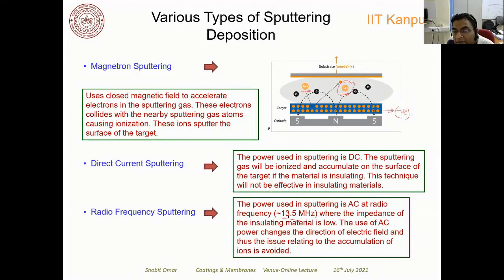Also, the use of AC power changes the direction of the electric field, and this will prevent the issue of accumulation of ions on the cathode material, because when we change the direction of the electric field, these ions can be easily removed from the surface of the target material. So that's why we use the radio frequency sputtering technique.